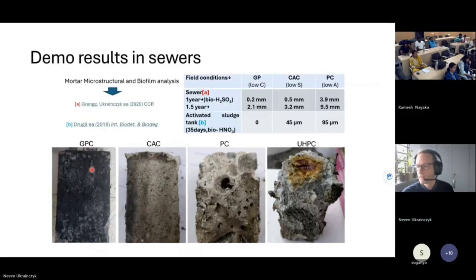Yeah, you can see here also the field conditions. We also did the activated sludge tank. This is the wastewater treatment where we have the biogenic acid, and the geopolymers were always performing the best, even when you compare with calcium aluminate cements, which are 3 to 4 times more expensive than Portland cements. It depends also on the mixture. Geopolymer is more expensive, but it's more durable.